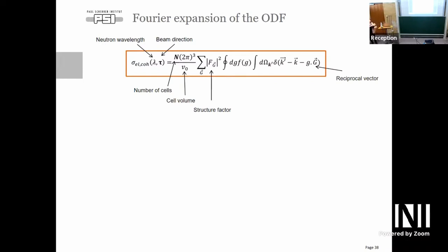For example, for an alloy, you can assume that every atom in your cell is composed of the volume fraction of your alloy. If it's an ordered structure, one particular position will be linked to one particular atom and another position will be linked to another atom, and that will change your structure factor. So you have to know how your crystal is. Yeah, you have to know your material. Right. Sorry, carry on.